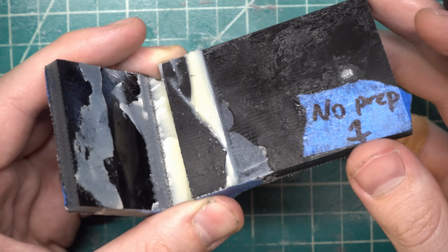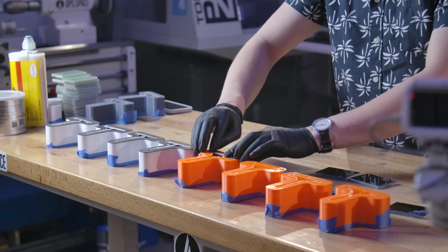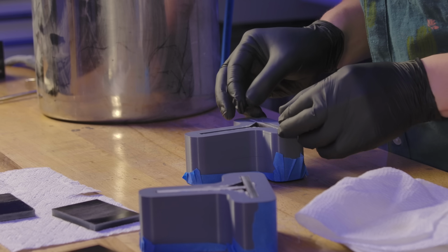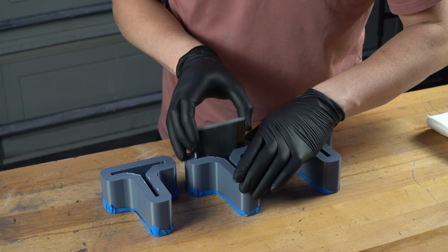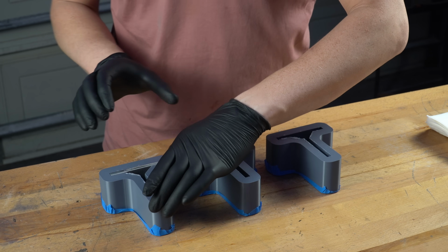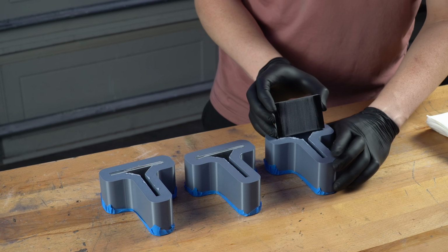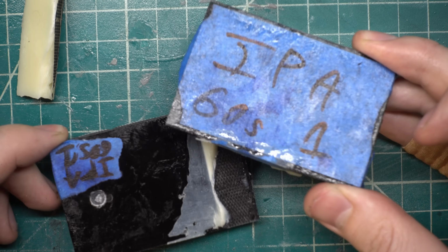I should also mention these parts are still covered in superlube. When I place them in the mold, I'm extremely careful to not let any of the superlube touch the surface. It's possible in all these tests that there's a little superlube contaminating the epoxy, but I largely doubt that this is the case. Looking at the 60-second IPA sample, we see two different failure modes.